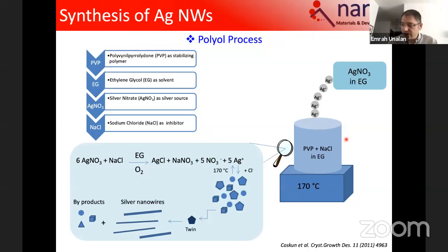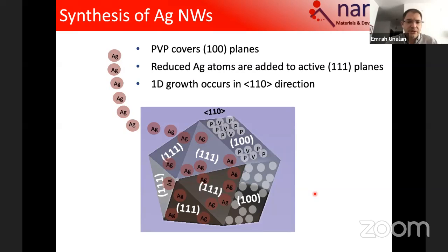So let me switch the gears and start talking about how we make these materials. So we make use of simple solution-based processes, for silver and copper, and I will further discuss the copper later on. And for silver, as you see, we just mix chemicals, we do some temperature adjustments, and growth is a bit different than conventional FCC structured silver. So in here, rather than having a cube, we're having a pentagon. So we start with multi-twin particles, and a polymer dictates or controls the growth direction, so that the newly added silver allows you to grow in 1D to get a nanowire eventually.